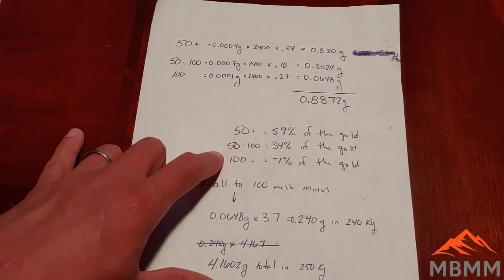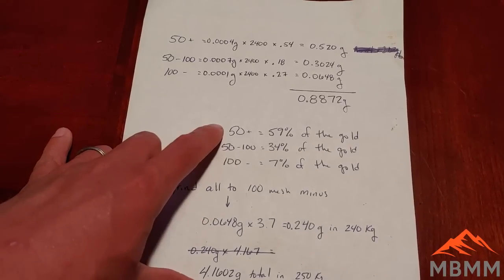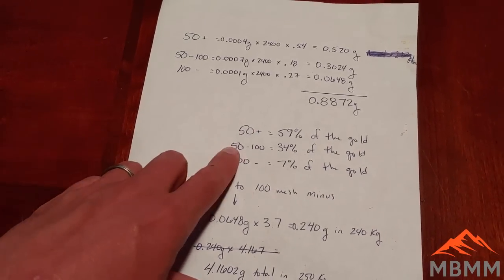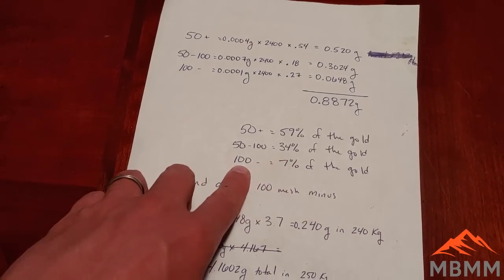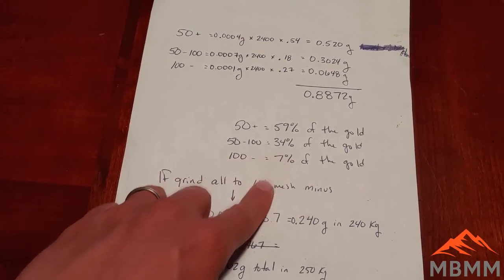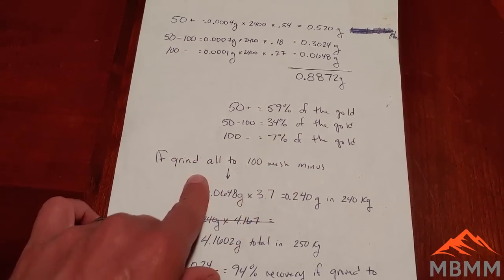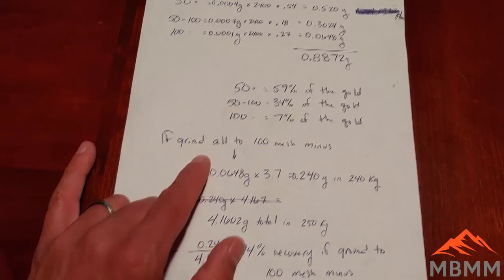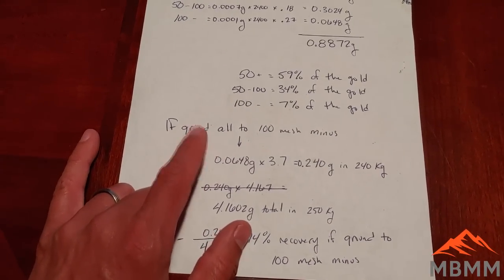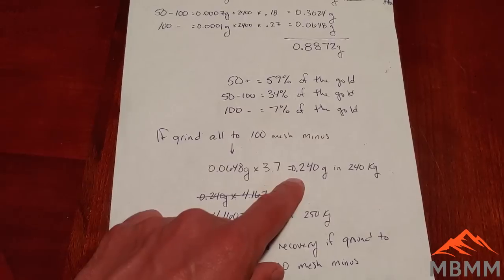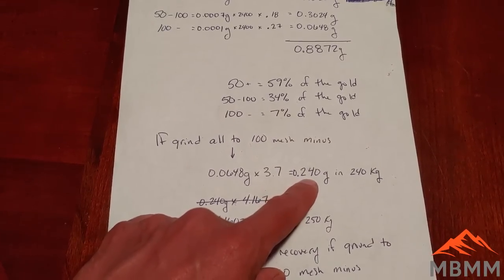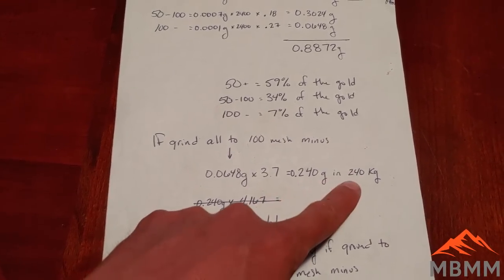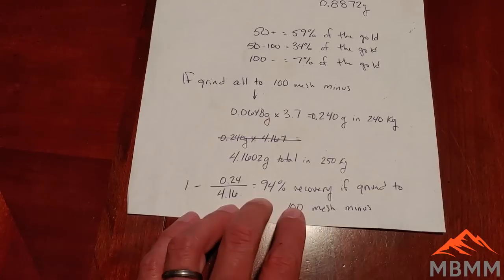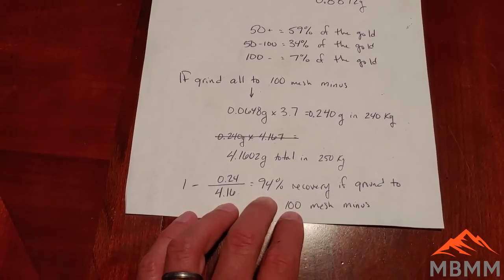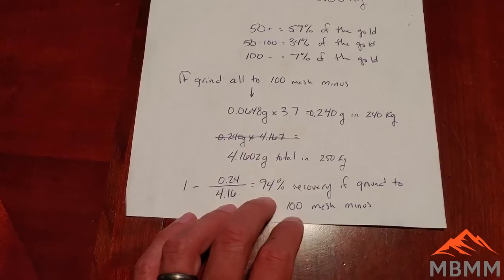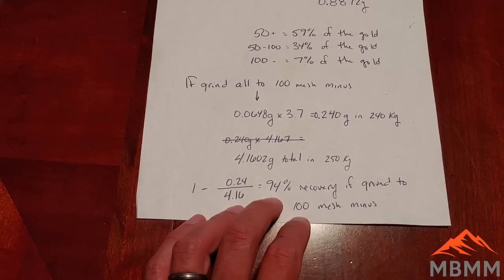And then here's the percentages of where the gold is. So 50 plus has 59%, 50 to 100 has 34%, and 100 minus has 7% of the gold. And so now, kind of continuing on our train of thought here, if you ground all the material to 100 mesh minus and you end up with 0.240 grams of gold in 240 kilograms, you would end up getting about 94% recovery if you ground it all to 100 mesh minus.